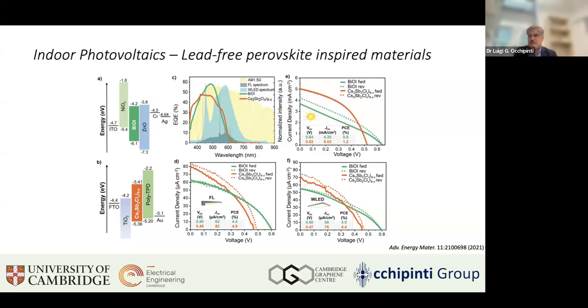Critically, both these compounds have an optimum band gap in the range of 1.9 electron volt, specifically 1.93 for bismuth and 1.95 for antimony-based compounds. Another feature which was well explored in this paper is that they have a layered structure rather than a zero-dimensional crystal structure, which contributes to improved charge mobility. And ultimately, this also impacts the efficiency of these absorbers.